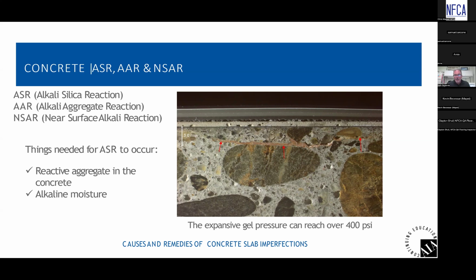Now, it is a form of a pop out, and I'll tell you this, nobody's going to be able to visually look at a pop out and say, hey, this is ASR or NSAR. Okay, you got to send to a third-party lab and have them test to evaluate that it is ASR. And unfortunately, if it is ASR, it's basically the concrete has cancer. So if there's aggregate at the surface, there's probably aggregate at the middle that's reactive. There's aggregate at the bottom that's reactive. Unless you can be 100% sure that you have remediated all chances of liquid water in that concrete, then there's always that potential for ASR no matter what you do.